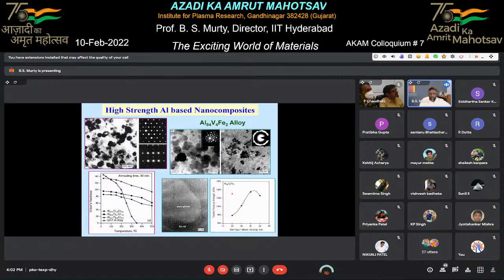It is not only possible to do that, we are also now able to get materials which can withstand their strength even at high temperatures. These are some aluminum alloys. We are now making what we call aluminum based super alloys, where an aluminum alloy retains 90% of its strength almost up to about 400 degrees centigrade or 500, close to 500 degrees centigrade, which is very close to its melting point. Aluminum melts at 660 degrees centigrade. So even at 0.75 or 0.8 of its melting point, its strength is almost 80% of its original strength at room temperature. All this is possible by embedding nanoparticles into aluminum.